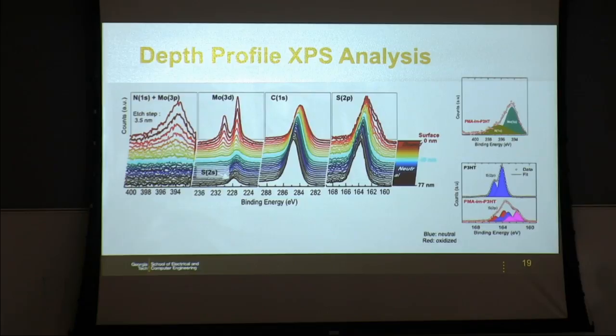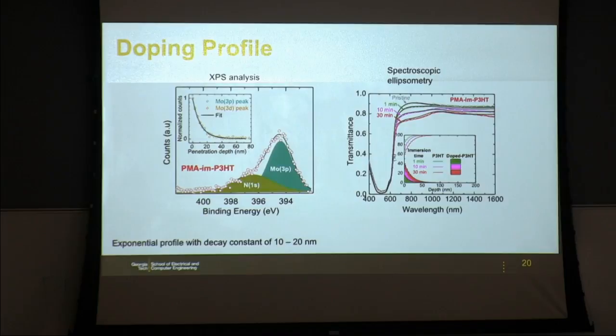And so the film becomes charged, it becomes more ionic in nature, and that controls the diffusivity of new dopant molecules. And so there is an action-reaction process until you reach a steady state, and this actually gives you a doping profile which is exponential. And you see that the typical profile here, the depth here is an exponential profile with a typical decay constant of the order of 10 to 20 nanometers.